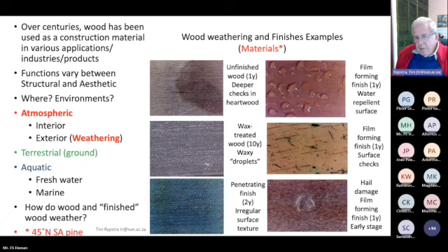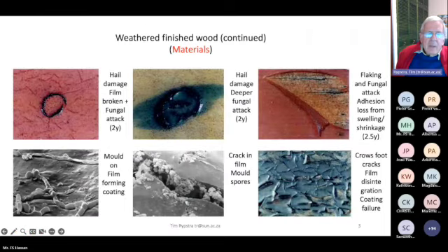Then perhaps something funny, but it happens: hail damage on a film forming coating, starting off with a little scratch or a circular scratch like that. After 1 year that happened. Next slide, please. Proceeding to a darker accentuated ring, which is then already indicating some fungal growth over there.